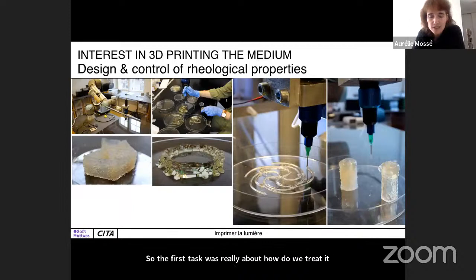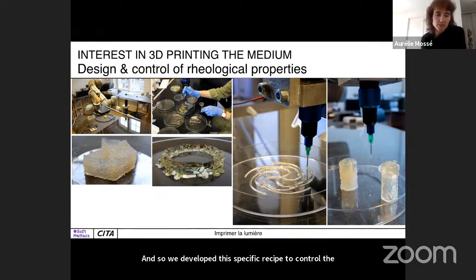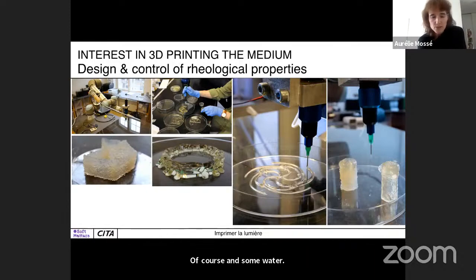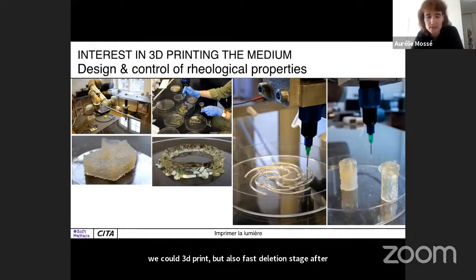So we developed a specific recipe to control the rheological property of the medium. The medium here is based on a mix of agar, gelatin, nutritive media, of course, and some water. And really the key point was to find the balance between the need of a relatively important viscosity so we could 3D print, but also fast gelation stage after extrusion so we can build firm structures, but also structures that develop in height. So for that reason, we actually used household agar rather than a lab grade agarose.